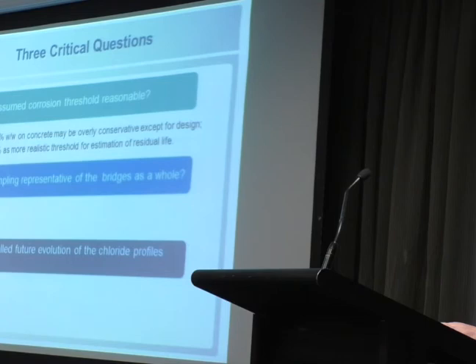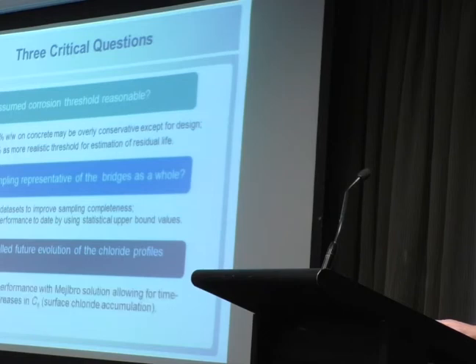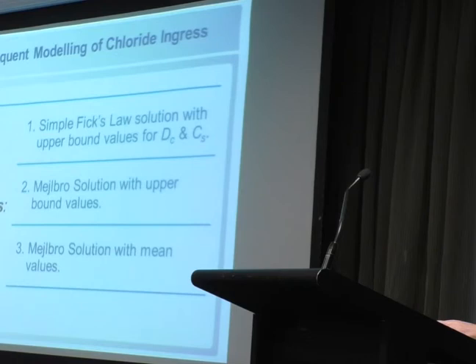So, answers to those questions: Rees assumed very conservative values, which may be appropriate for design, but possibly if you're talking about maintenance interventions, you could accept a higher chloride concentration threshold. Is the sampling representative? Well, we combined additional data with his, and we characterized the performance by using upper bound statistical values. And is the modeled evolution of the chloride profiles credible? Well, I think you've got to at least look at the Mejlbro solution, allowing for a time-dependent increase in the surface chloride concentration as another option, which is basically what we did.